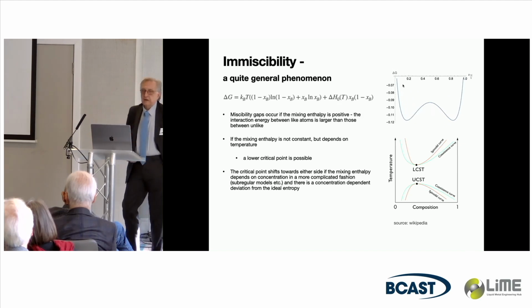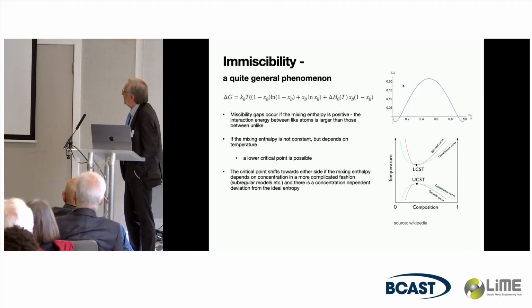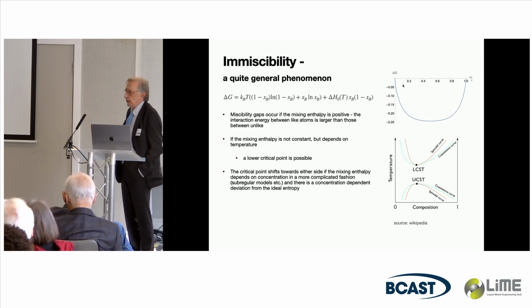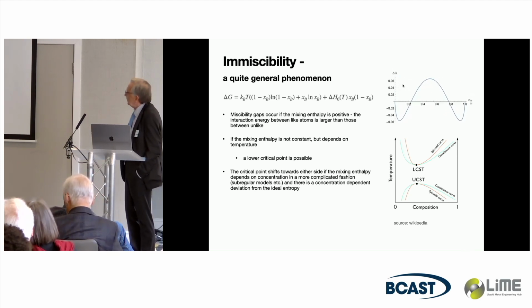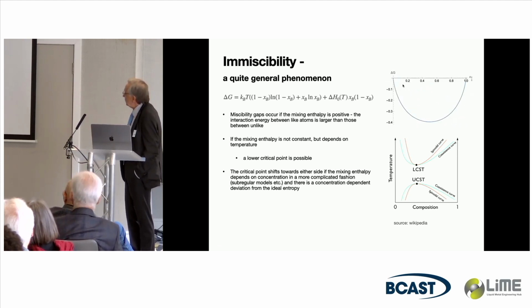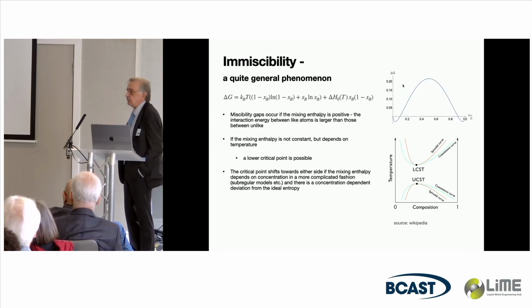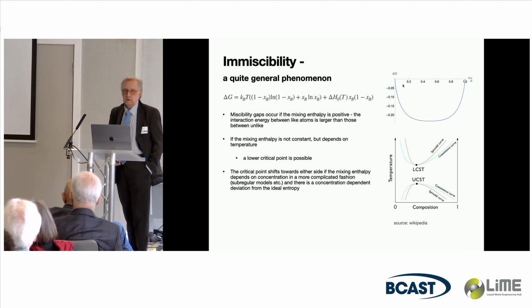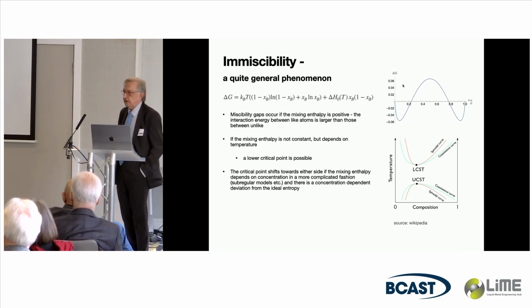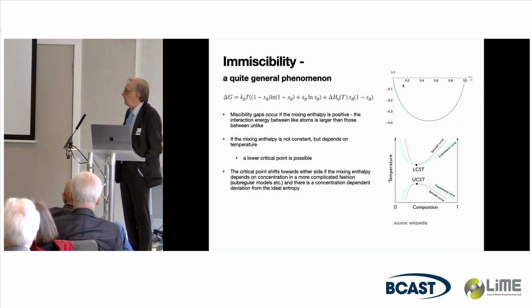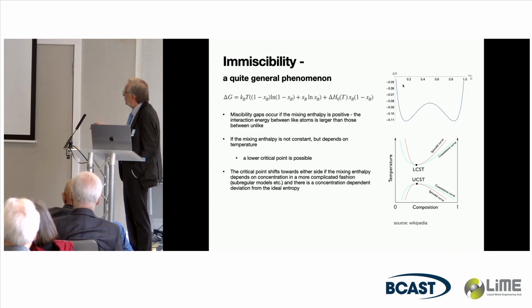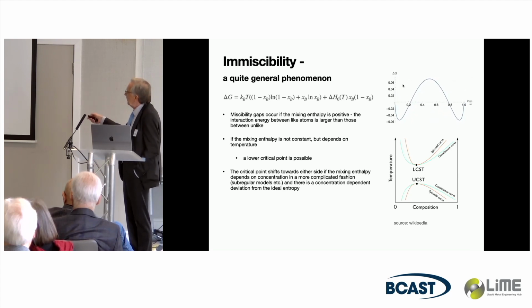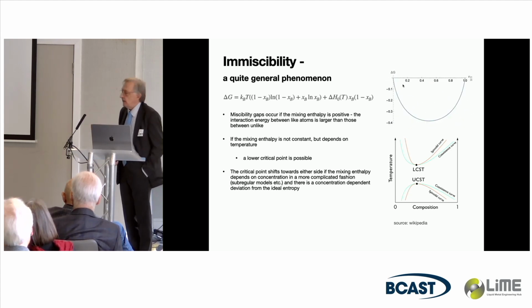This is very simple: like atoms like each other more than different components. The point is, in reality, in metals you always see a miscibility gap with an upper critical point. I do not know of any example which has the opposite. But in organics, you also have systems with a lower critical point, and I'll show you an example of that later. This is due to the enthalpy of mixing depending, for instance, on temperature.